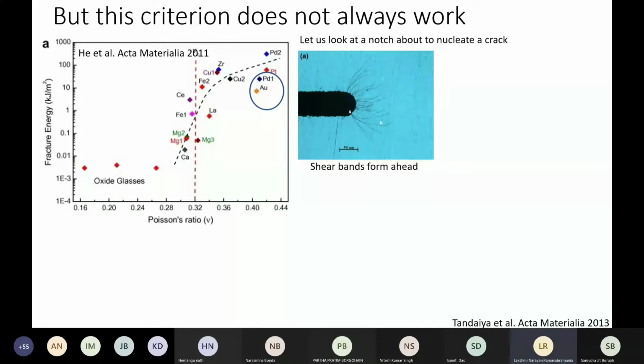So there is a stress concentration, and obviously ahead of the stress concentration, when you apply load, remember that the load is being applied in mode 1, which means that you can assume that in the plane of paper, this notch is being loaded. Essentially force is being applied vertically to this particular picture. So you see several shear bands that are formed in front of the notch tip.